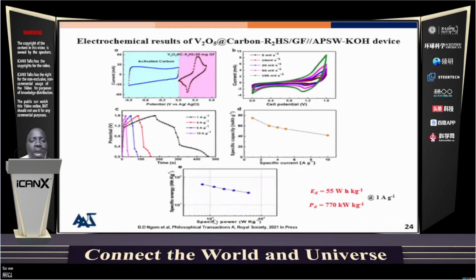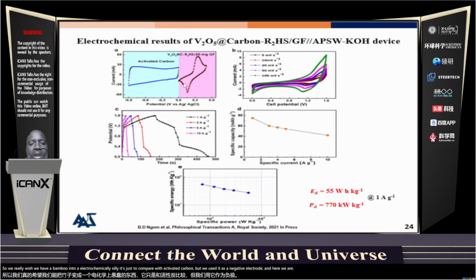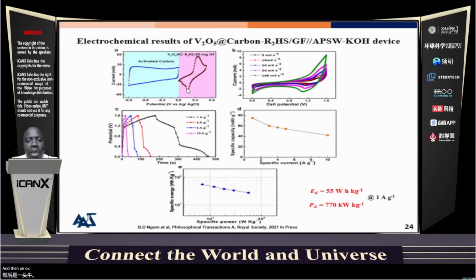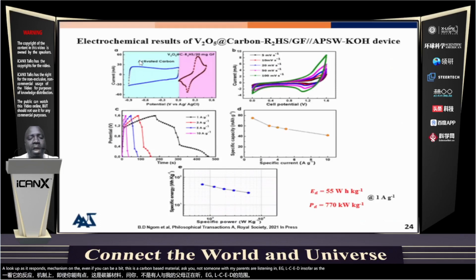So we have done the electrochemical CV. Here is just to compare with the activated carbon that we used as a negative electrode, and here we are having the composite, and you'll see the oxidation and the redox peaks that we're having here, which show exactly that we're still having a supercapacitor response mechanism on the material. Even if we imbibed this carbon-based material, as we know, the carbon-based materials are responding in EDLC form, as the activated carbon is showing no oxidation or no redox peak.